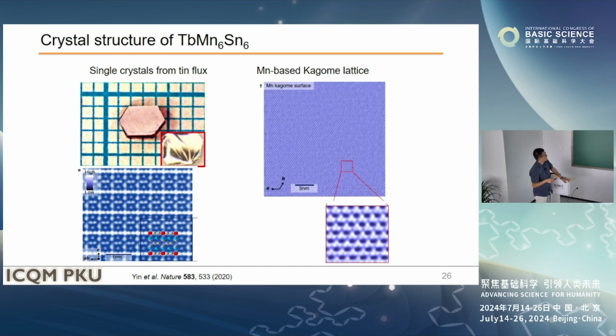So this is our compound. We grow the crystal from tin flux, and the crystal is very beautiful with a hexagonal shape. And this is our collaborator doing some STM and TEM measurements to confirm that you actually observe the manganese-based kagome lattice, and from the side you see a clear layer structure of this compound.